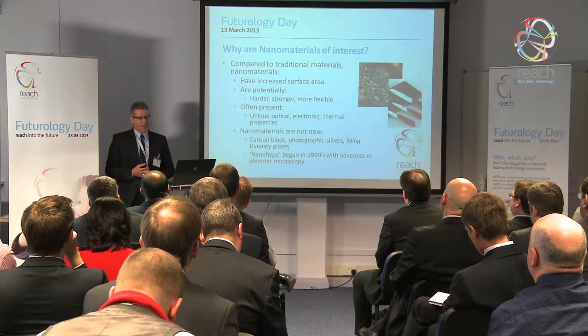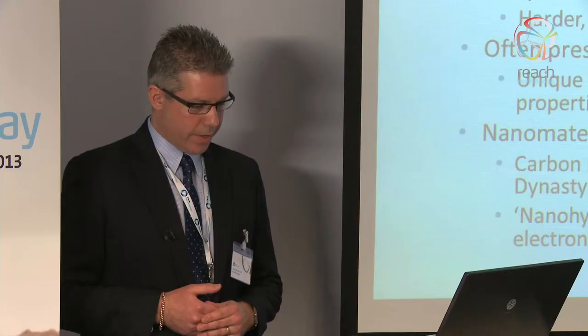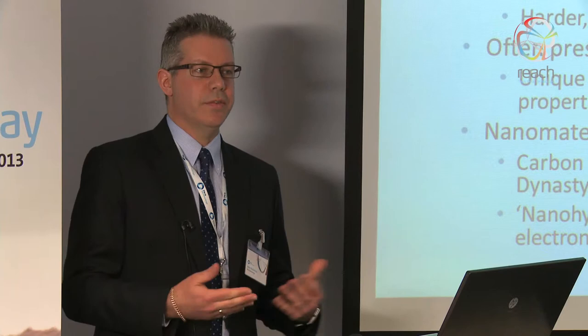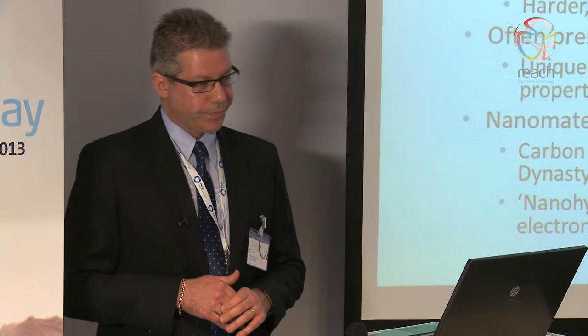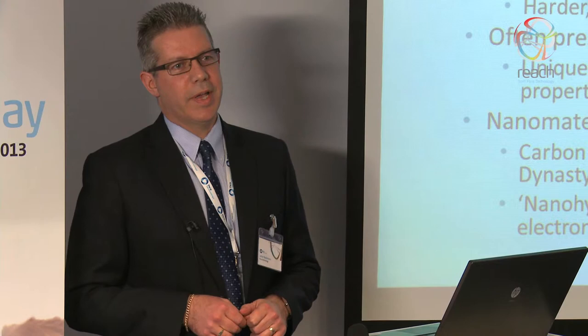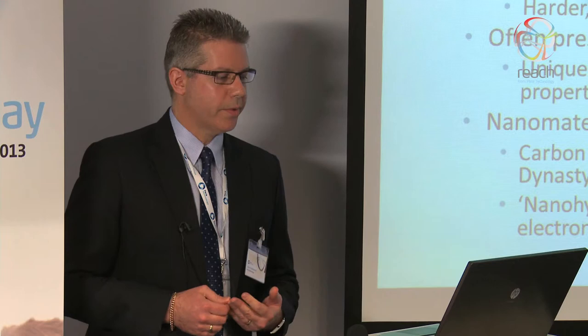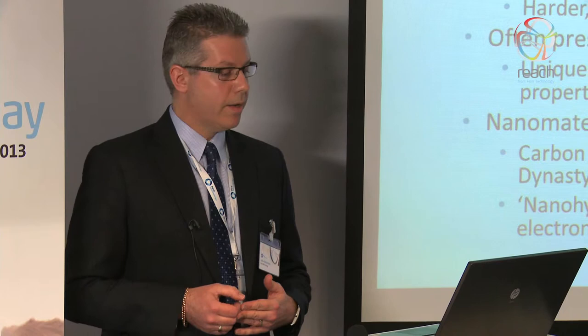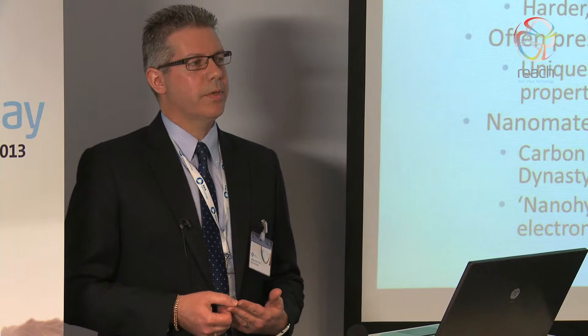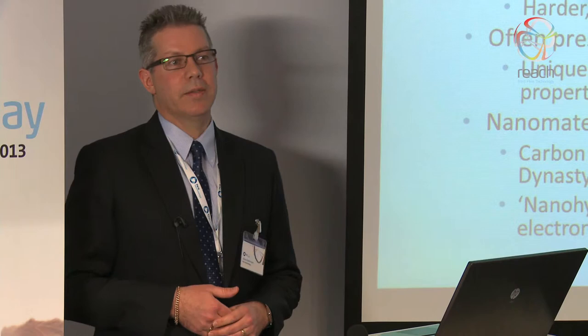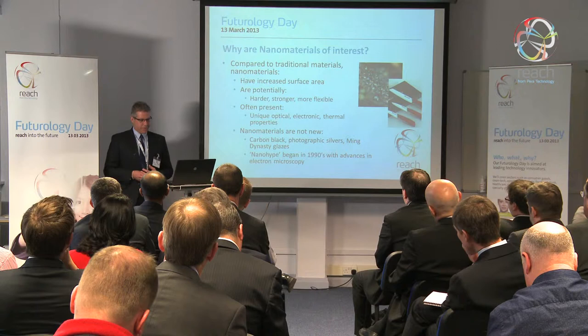Why are we interested in all this, and why do scientists get so excited about nanomaterials? It's because compared to more traditional equivalent materials, nanomaterials tend to have some very unique and exciting properties. They generally have very high surface areas, which accounts for a lot of these exciting properties. Depending on the material, nanomaterials potentially are harder, stronger, even more flexible than more traditional counterparts, and often display unique optical, electrical, thermal, and magnetic properties. One interesting feature is that once the size becomes below a certain limit, the particles actually become transparent in dispersion, giving rise to some very interesting applications like transparent coatings.